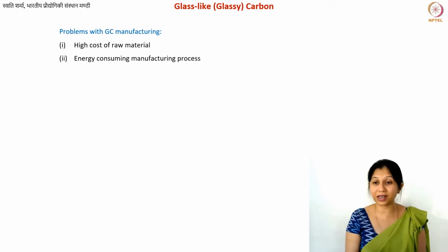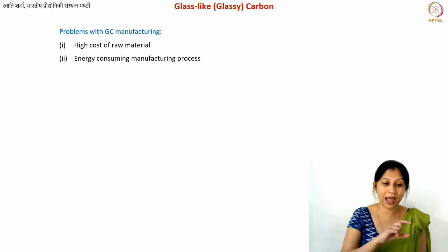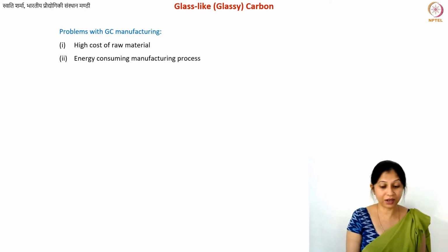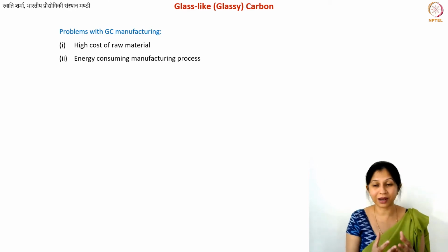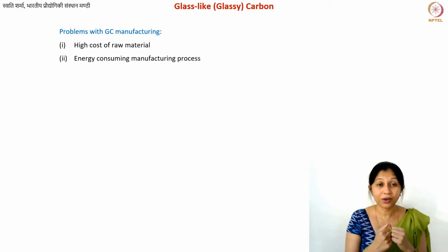Plus, you cannot even heat it very fast. The heat treatment rate is known as the ramp rate. If your ramp rate is slower, then you get better quality carbon. So you would like to heat it slowly, which means just think about the energy consumption of the overall process. So this makes your material itself very expensive.